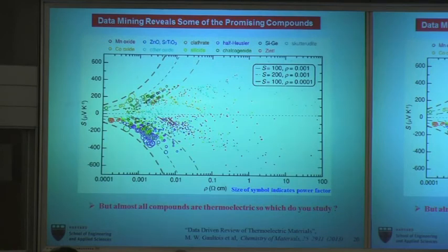The other thing you can do with data mining is to try and identify which sort of composition you should be working on if you want good materials. So this is a rather complicated graph, but it's a plot of the Seebeck coefficient, and we either want a high negative or high positive value as a function of resistivity for all the materials that we could find in the database, and that's several hundred different compositions. The ones with the big circles are the ones that have a high power factor. And what you want to be able to do is have ones that are on these parabolic curves.